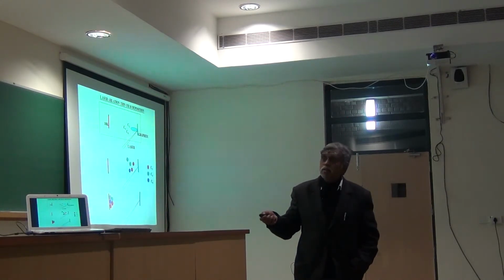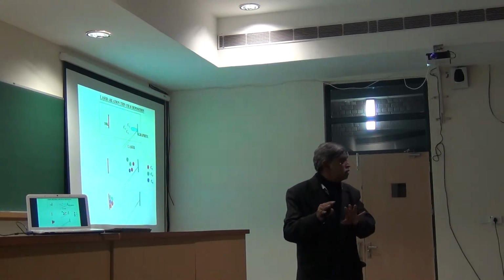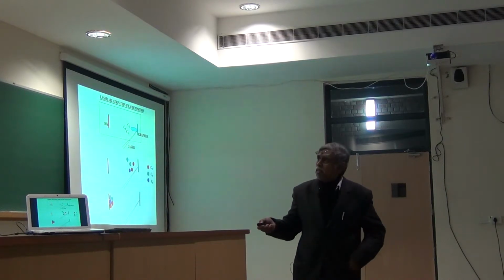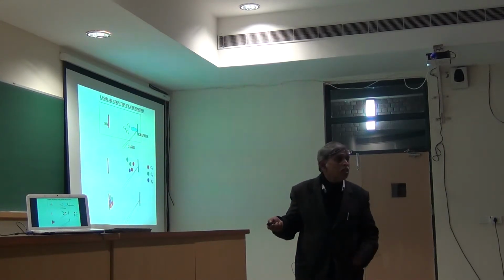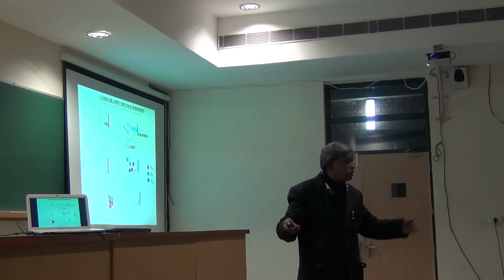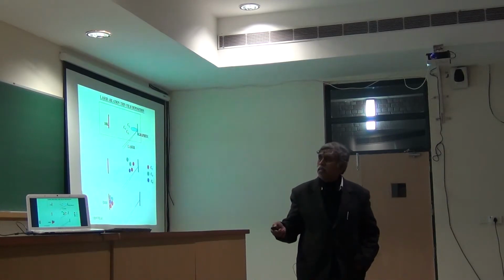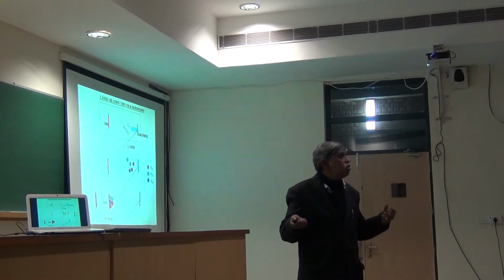In this experiment, they are not sending argon there, so there is nothing to insulate them. So when these species actually go and deposit onto your substrate, they are sitting right next to each other. They are all reactive, so they will all react with each other. And what will you get as a result? You will get a thin film of graphite once again. So this is how thin films are produced by a laser ablation process.